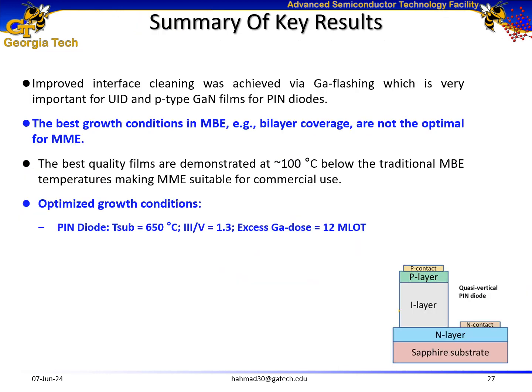To summarize the key results, I introduced a gallium flashing technique to improve on rigorous interface cleaning for UID gallium nitride films and also for p-type films for pin diodes. I found the best growth conditions in MBE are not necessarily the optimal for our MME growth technique, and I demonstrated the optimal growth conditions at approximately 100 degrees C below the traditional growth temperatures, making MME suitable for commercial use. Furthermore, I found the optimal growth conditions for my pin diodes.